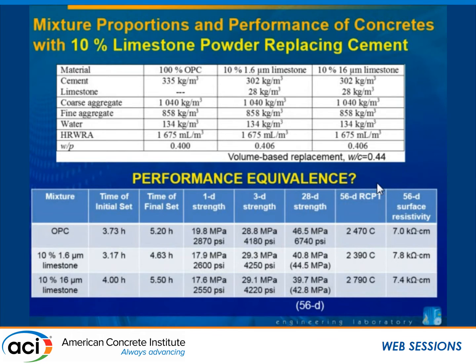Setting times are approximately equivalent. However, strength values at 1, 3, and 28 days are tracking below OPC concrete. But our rapid chloride permeability and surface resistivity measurements are approximately the same, indicating we're not changing the microstructure or capillary porosity too much. This was done with two different median diameter limestone powders, and with the finer powder we observe a slight accelerating effect with the limestone.